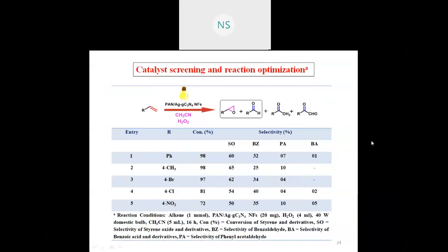That is the catalytic screening and the reaction optimization we have done. And in the optimization, the second table, the second entry shows 98%, 65% of styrene oxide. Upon changing the R position of that particular styrene, that is the alkyl group changing, we get that particular conversion rate: 98% in case of the phenyl, and in case of the CH3 group, that is 98%. And when we change to 4-Br, 4-Cl and 4-NO2 at the 4 position, it shows 97, 81, and 72%. But in case of the 4-CH3, the conversion is 98%, but the styrene oxide is more as compared to the others. It is up to 65%.